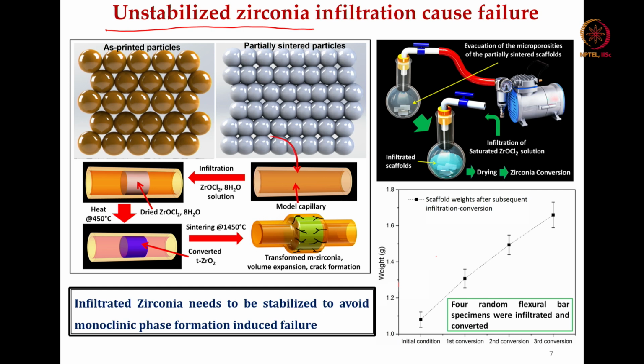You can see this is the binder jet 3D printed structure, this is the 3D printed sample. You essentially evacuate the microporosities of the partially sintered scaffolds, and after that you put it there. Then you add the infiltration of saturated zirconium oxychloride solution into it. Then you do the infiltration treatment, after the drying, sinter it for the zirconia conversion. So, you have the as binder jet 3D printed particles, and this is your partially sintered particles.